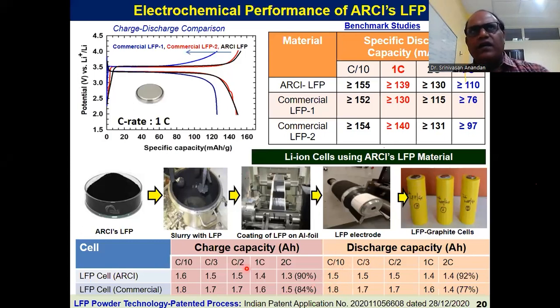So what we have done is compare the performance of a cell made from commercial LFP material. This is the capacity of the ARCI cell, which is giving 1.5 ampere hour, whereas the cell made from commercial LFP is giving 1.8 ampere hour, slightly higher than the ARCI cell. But if you look at the capacity retention, the ARCI cell could retain 92% of initial capacity, whereas the commercial cell can deliver only 77% of its capacity.